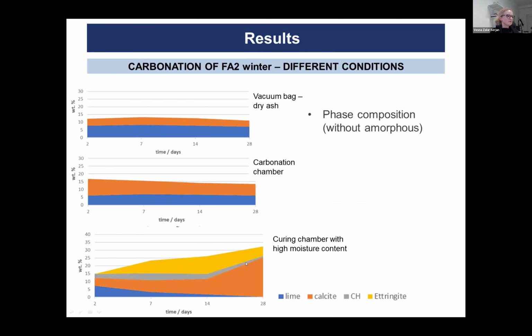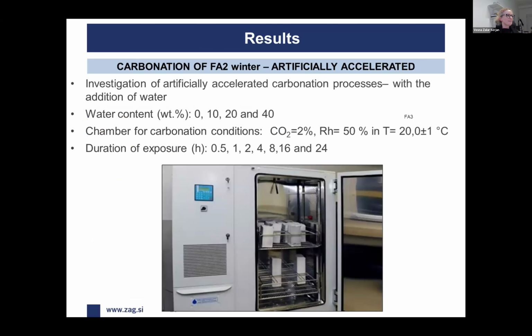The results show that, of course, the curing chamber with high moisture content was the most efficient during the carbonation of the material. We can see the depletion of lime, while the quantity of calcite increased, and the quantity of portlandite decreased. On the other hand, some hydration products also formed, which is the result of contact with the moisture, as we already showed before.